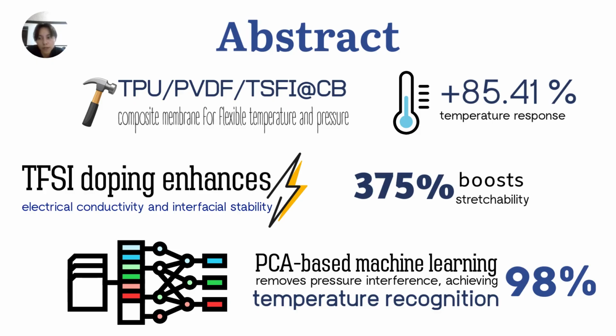It proposed a solution-based method using TPU, carbon black, and the ionic liquid TFSI. This was incorporated into a PVDF to form a flexible composite capable of sensing both temperature and pressure. The resulting sensor shows improved conductivity, enhanced interfacial stability, and stretchability up to 375%. It performs reliably in human motion tests, and with machine learning and PCA, pressure interference can be effectively removed, reaching 98%.